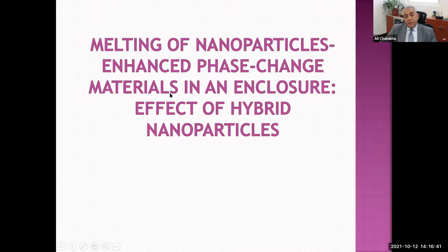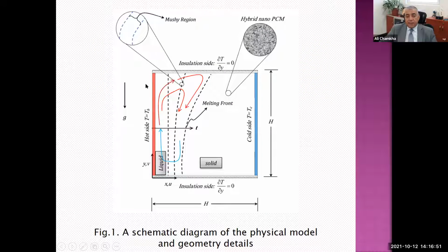Now I go to an important problem, which is melting of nanoparticle-enhanced phase change materials in an enclosure, the effect of hybrid nanoparticles. We use hybrid nanoparticles. This is a cavity that has phase change material, hybrid nanoparticle material, and you will have a heated surface and a cold surface. As the mixture melts, you will have a liquid part here, a solid part that's not melted, and a melting front that's moving in this direction.